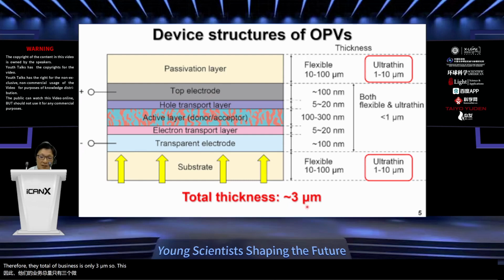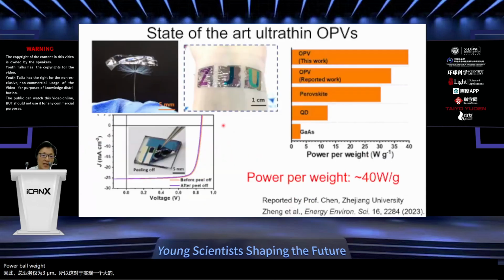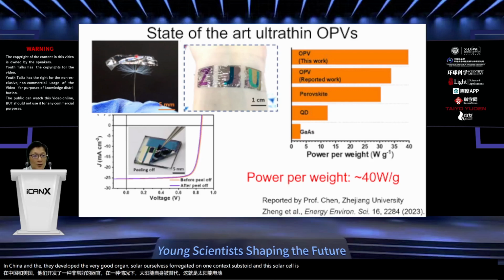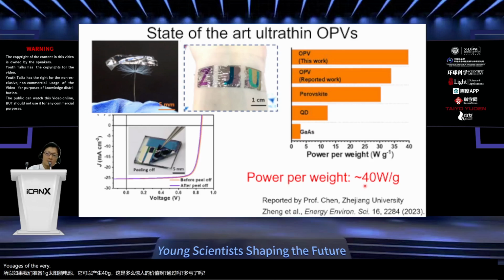This is very important to achieve a large power per weight. Here is a state-of-the-art ultra-thin organic solar cell reported by Professor Chen's group in China. They developed very good organic solar cells fabricated on a 1 micron thick substrate. And this solar cell is very lightweight, as shown here. It has a very large power per weight value. The calculated value is reaching 40 watt per gram. So if we prepare 1 gram of solar cells, it can generate 40 watts. This amazing value can be achieved thanks to the usage of the very thin substrate and the organic semiconducting materials.